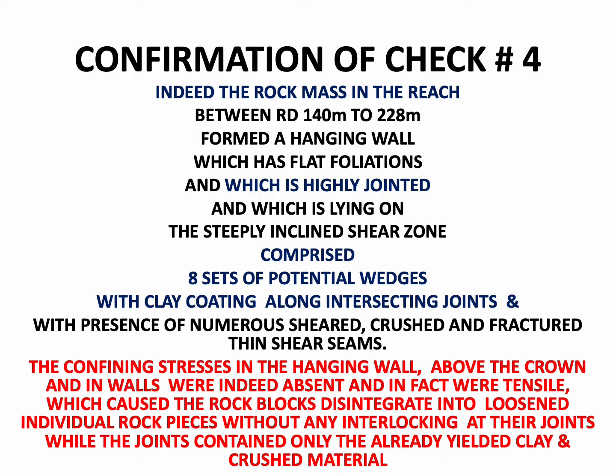So this confirms the fourth prerequisite check also, that indeed the rock mass in the reach between RD 140 to 228 meter formed a hanging wall which had flat foliations and which is highly jointed and which is lying on the steeply inclined shear zone, comprises 8 sets of potential wedges with clay coating along intersecting joints, presence of numerous sheared, crushed and fractured thin shear seams. Further, that the confining stresses in the hanging wall above the crown and in the walls were indeed absent and in fact were tensile, which caused the rock blocks to disintegrate into loosened individual rock pieces without any interlocking at their joints, while the joints contained only the already yielded clay and crushed material in them.